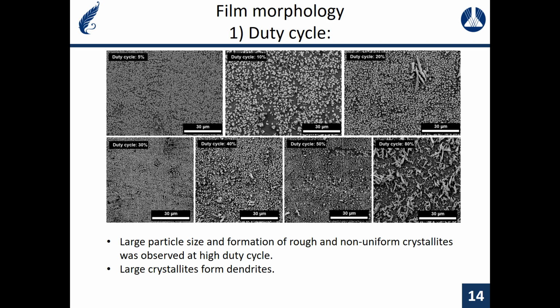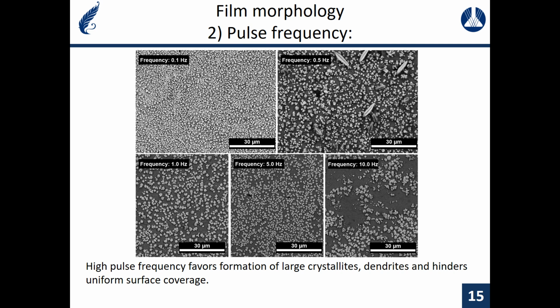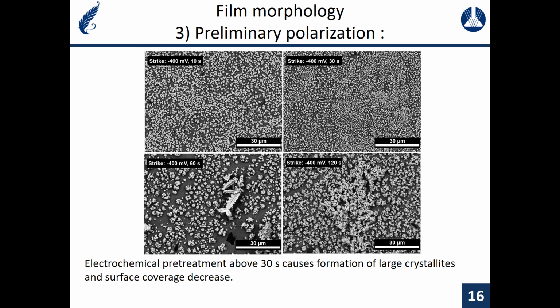The morphology of the electrodeposits was controlled by parameters of the electrodeposition. First, the duty cycle, which is the ratio of the cathodic and the anodic steps duration in the potential control waveform. The particle size generally increases with duty cycle, results in rough, non-uniform films at too high duty cycle. As for the pulse frequency, high values of pulse frequency lead to the formation of large crystallites and dendrites. In order to facilitate nucleation on bare substrate, the electrode has to be pre-polarized at the potential more negative than that used for film deposition.